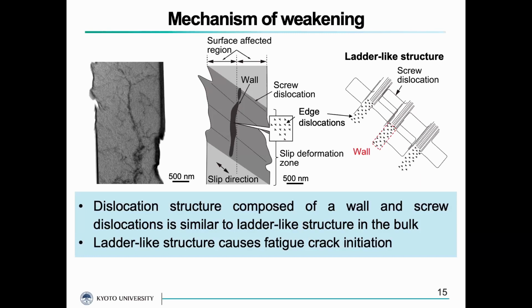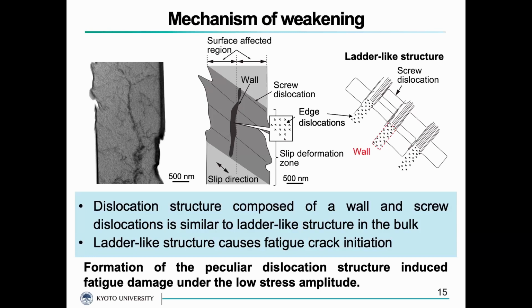Because screw dislocations in the low dislocation density region can easily move back and forth and produce larger plastic deformation, the formation of ladder structures causes fatigue crack initiation in the bulk. In micro-sized nickel single crystal, the peculiar dislocation structure similar to ladder-like structures was formed under low stress amplitude due to the influence of the size and surface. And the plastic properties of such a peculiar dislocation structure cause the formation of fatigue damage under low stress amplitude.